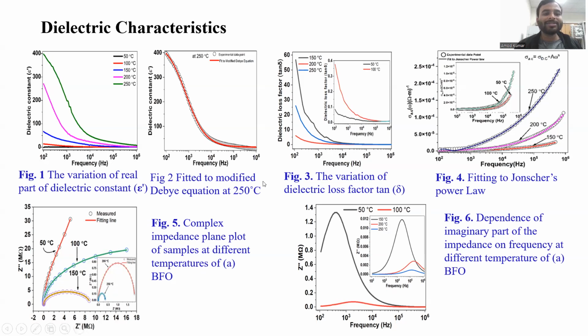This is the fitted graph, fitted to the modified Debye equation. Only the 250 degrees Celsius fit is shown in the figure. With the help of this fitting, I know about the spreading factor and relaxation time of the materials. Individually I fit all the temperatures, 50, 100, and others, but here I show only 250 degrees Celsius.